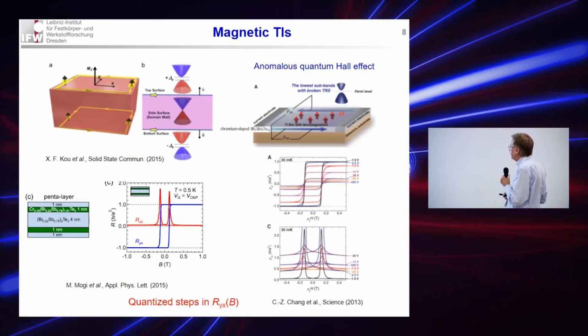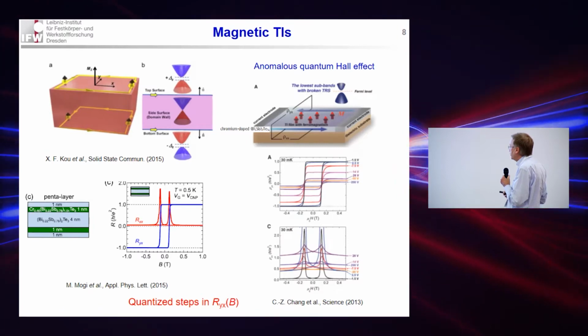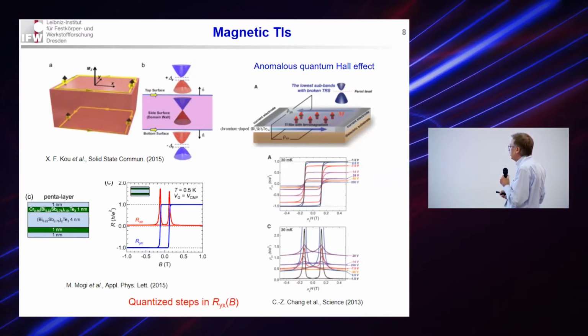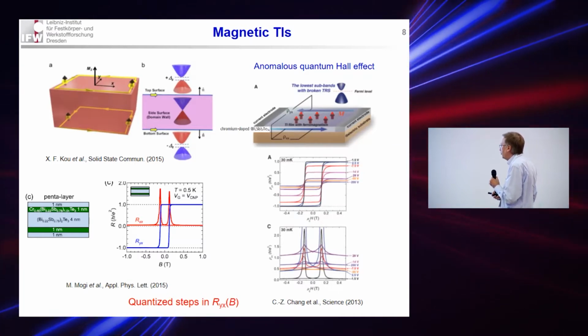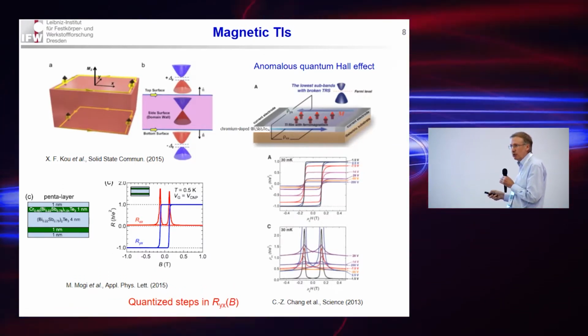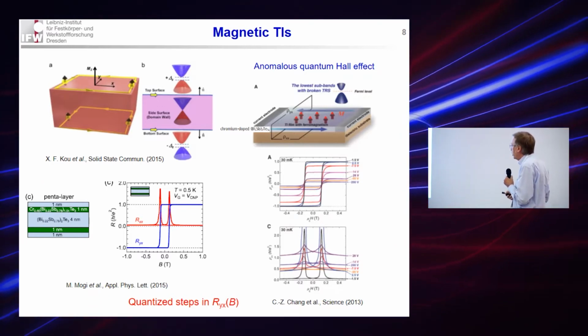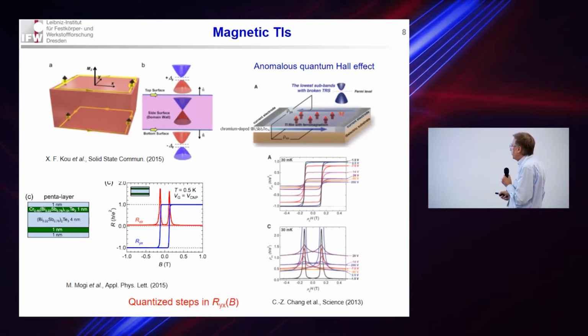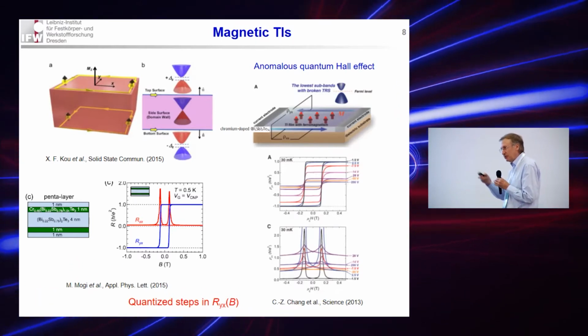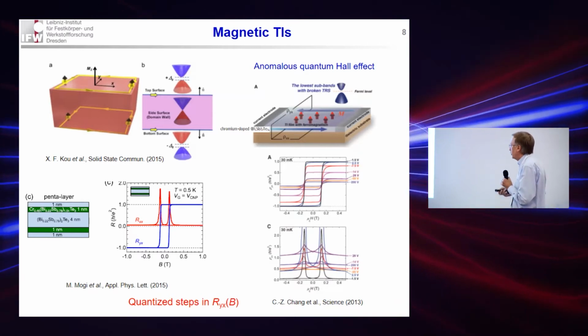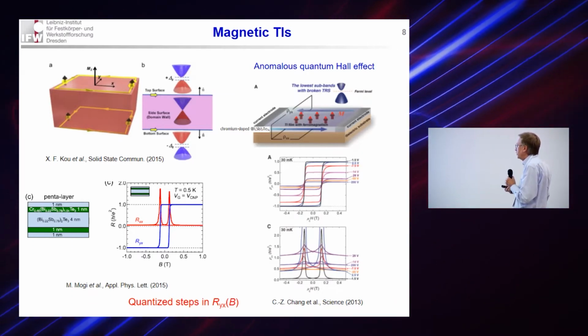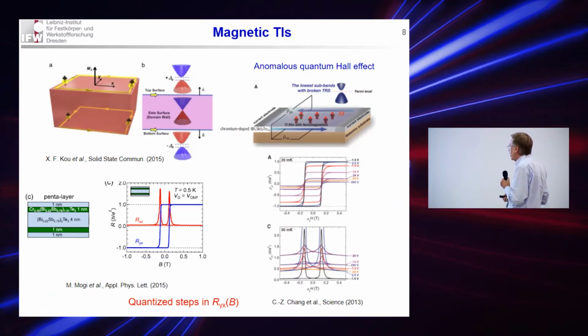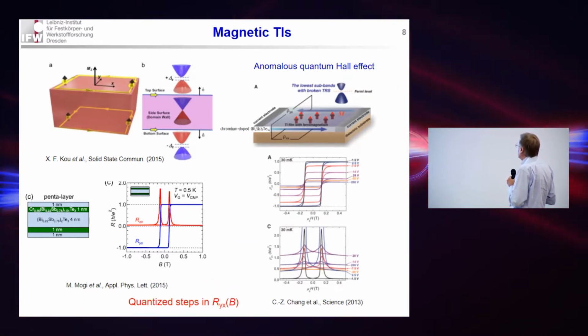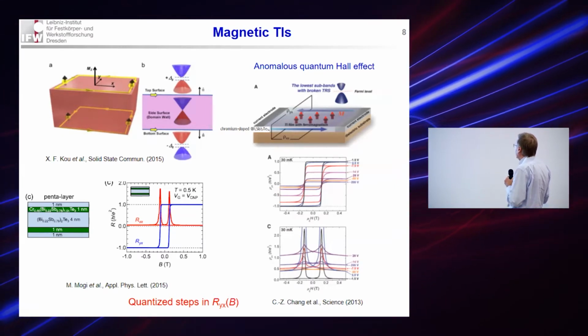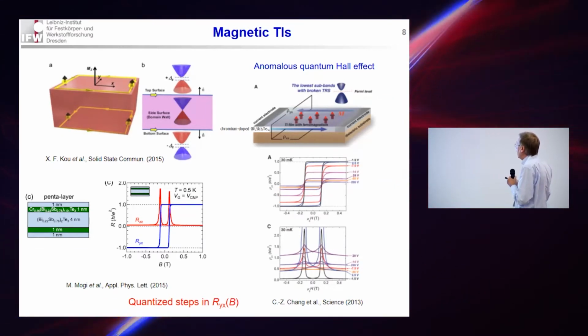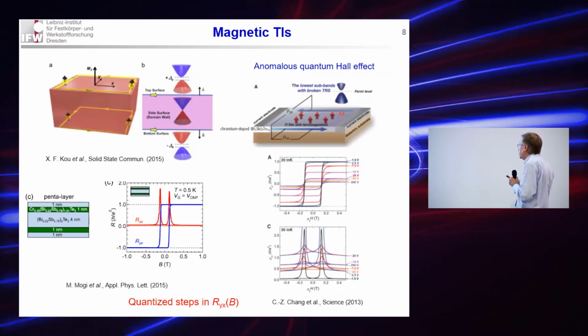So, for instance, in the Hall resistance, which is quantized in fractions of the fundamental unit, Planck's constant over the square of the electron charge. And the longitudinal resistance, as expected, diverges, getting to infinity. This longitudinal resistance is telling us that this material is insulating on the surface. The same was made also for this magnetically doped topological insulator, so the concept was proven.